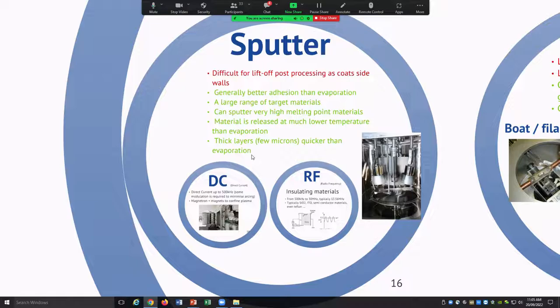Obviously it's a physical vapor deposition process. So you've got argon as your working gas. So you'll put argon into your chamber. It gets ionized. That ionized argon gets accelerated to your target. The argon is big and bulky, coming in with a fair bit of velocity. It hits your target, and then your target sprays it off. All of the atoms of that target get sprayed off and coat everything. So it is line of sight, but you're not actually melting the target, you're physically knocking the target material off. So if you've got a high temperature material like tungsten, then you can sputter it, whereas trying to thermally evaporate tungsten can be quite hard because you have to get it up to the melting point of tungsten.